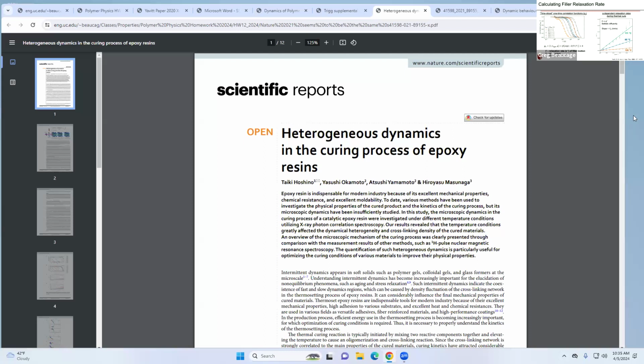So that is a way for us to analyze this process. We used a little bit different form. So we modeled this correlation function off of a stretched exponential that's defined by some parameters that have to do with our experimental setup. But the key thing here is really this gamma. That's the relaxation rate or the rate that that function decays at. It's the inverse of the relaxation time. The only reason we did that is because it's easier to write it on one line rather than have a division sign. The other key component in there is this beta value.